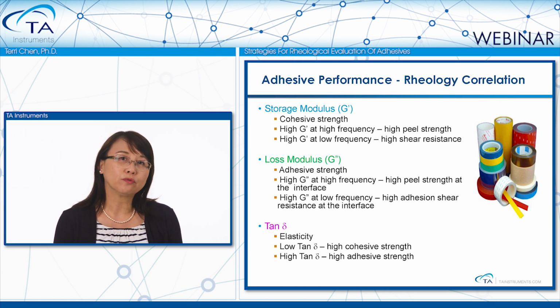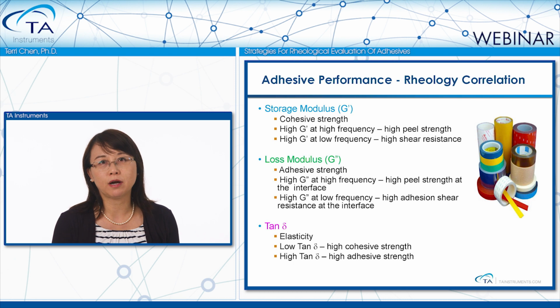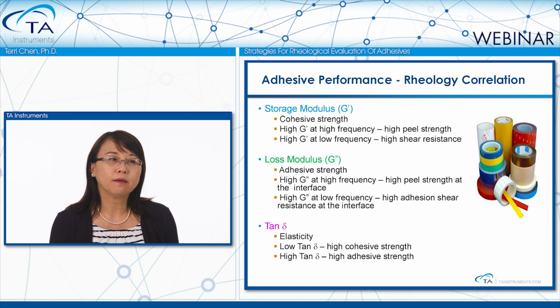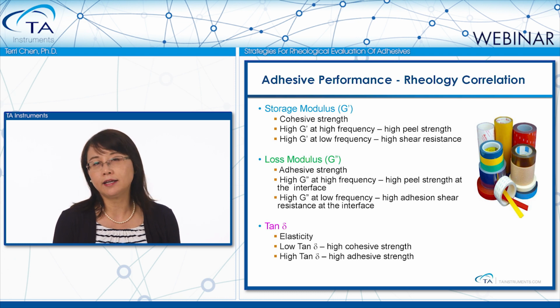Tangent delta is the ratio of G double prime over G prime. It measures the elasticity of a material. Low tan delta means the sample has good elasticity and high cohesive strength. A high tan delta means the sample is more damping and potentially has high adhesive strength.